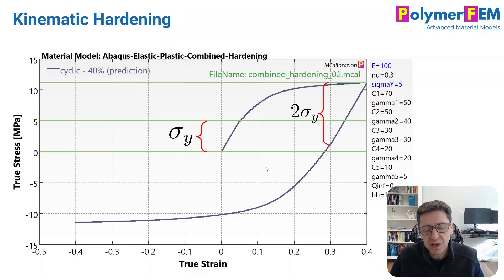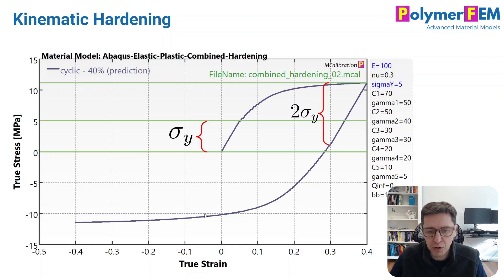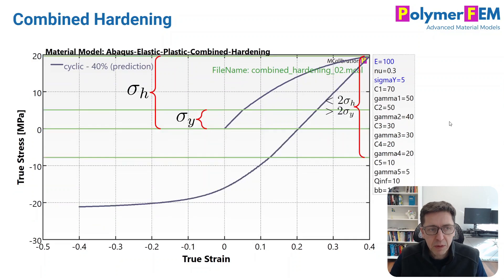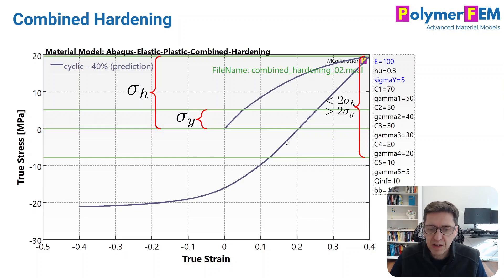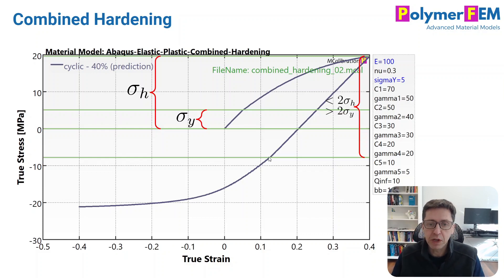Kinematic hardening plasticity is very different. The linear elastic response is followed by yielding, and then reverse plasticity starts at about twice that initial yield stress value — that's why you get linear elastic unloading and then a rollover, which is much more realistic for polymer predictions. With combined hardening, you can tailor the unloading response: the reverse plasticity point falls between the isotropic and kinematic hardening cases, which is exactly why it's called the combined hardening approach.